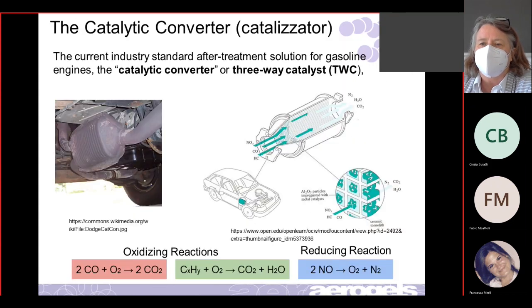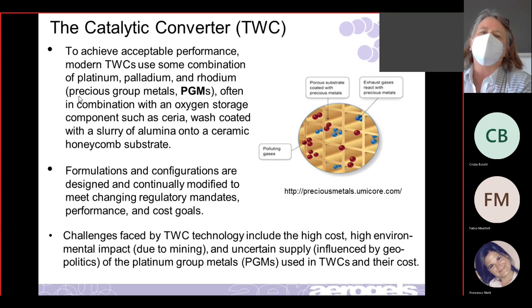And so the material they use on these catalytic converters is precious group metals, PGMs, that's what I'll call them. To work well, a three-way catalyst uses a combination of platinum, palladium, and rhodium. So the metal on these surfaces is that material, in nanoparticles, distributed in something else. It's not solid platinum, things like that. They often also have a component such as ceria. Ceria has the ability to store oxygen and then release it.